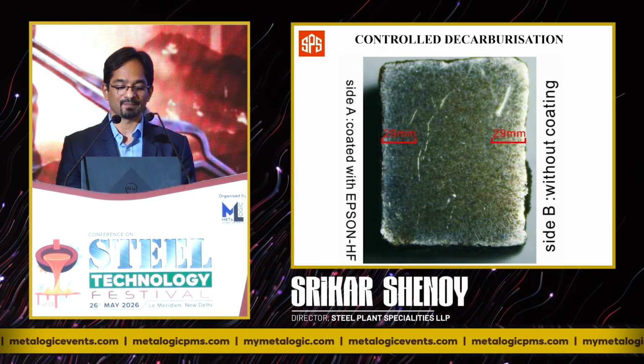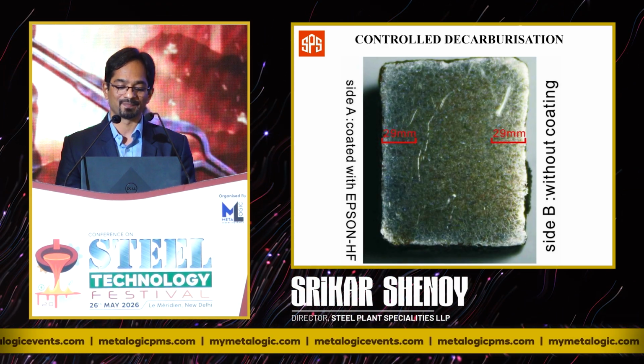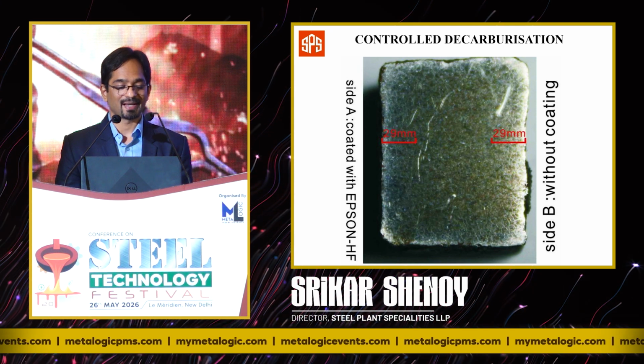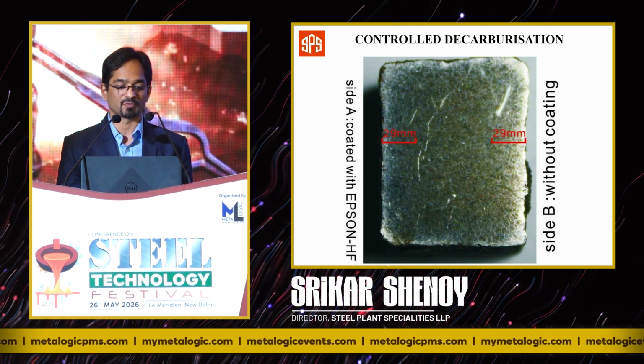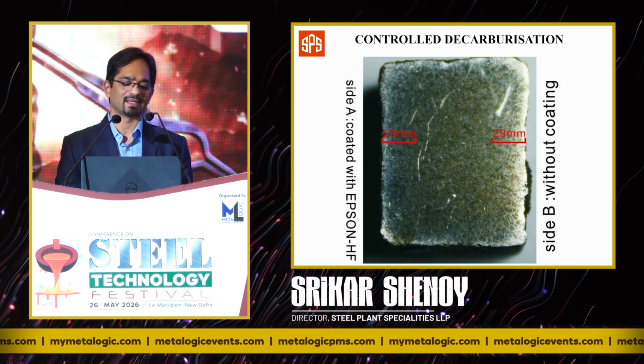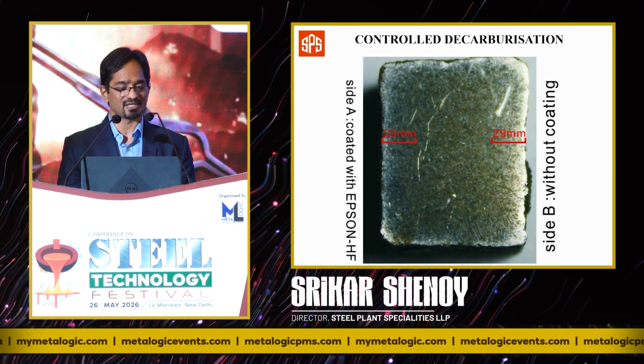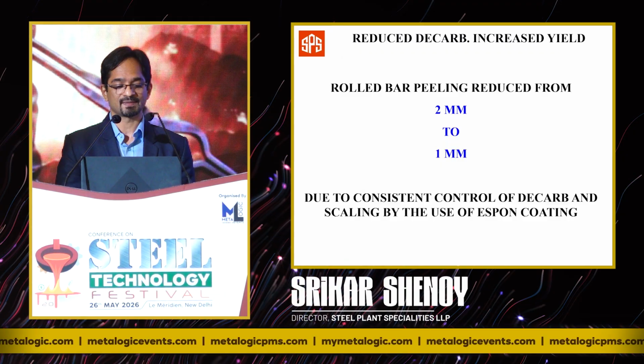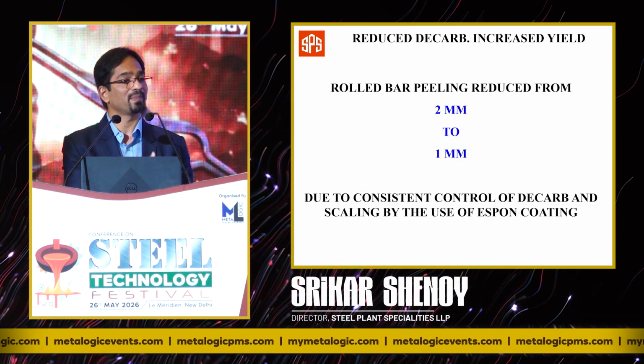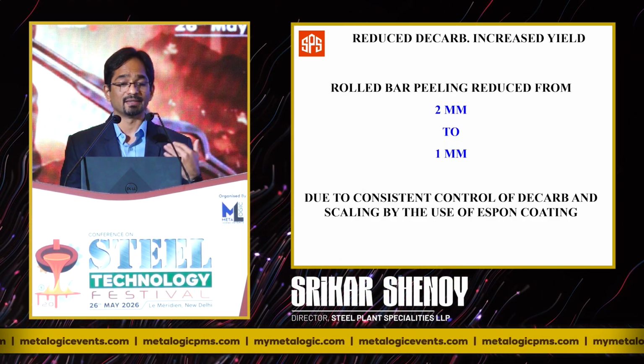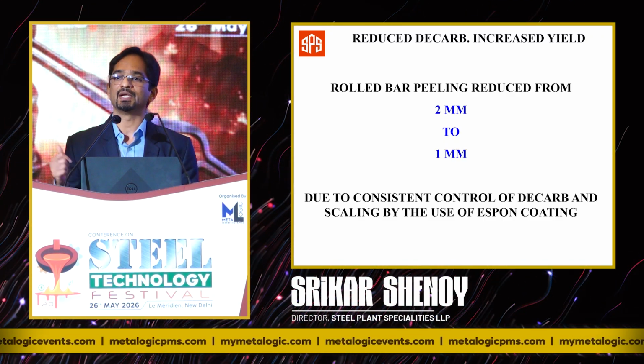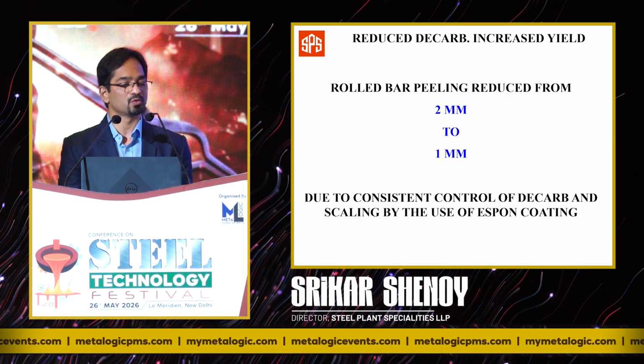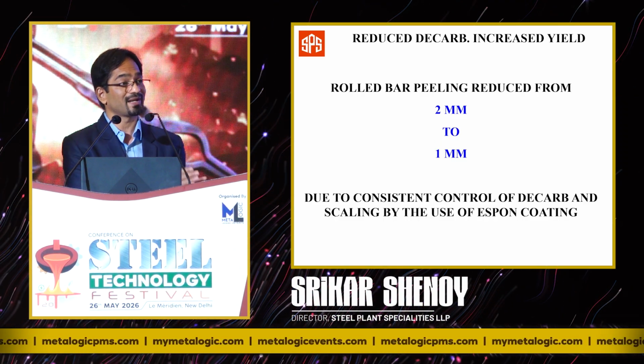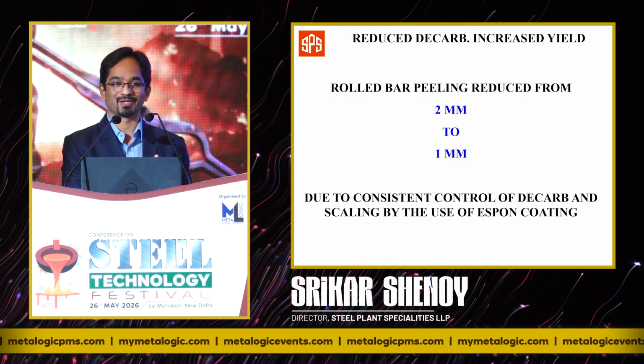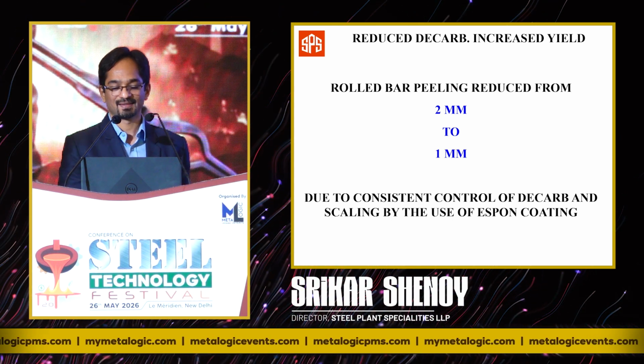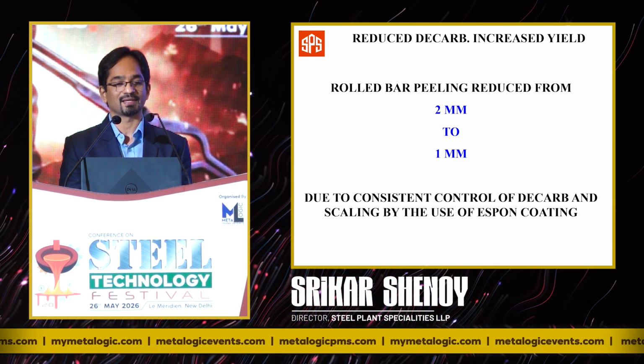This white layer that you're seeing is the decarb, which has penetrated. Now this is a surface deterioration, and it would have to be removed before the steel can be used further. On the coated area, you can see that there is very little or negligible decarburization. As a result of this, we've had customers who are peeling the rolled bars. They roll the steel, and they peel or remove 2 mm simply to remove the decarb and the scaling. So we've had customers who have gone from 2 mm peeling straight away to 1 mm peeling, with no capital investment, just coating the billets. No additional investment for increasing a peeling machine either.